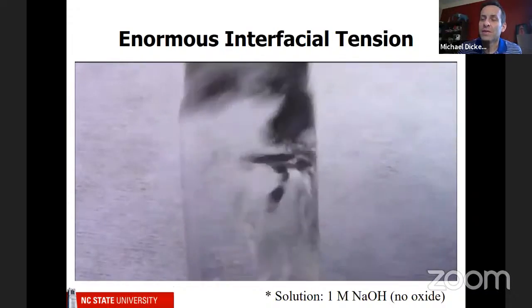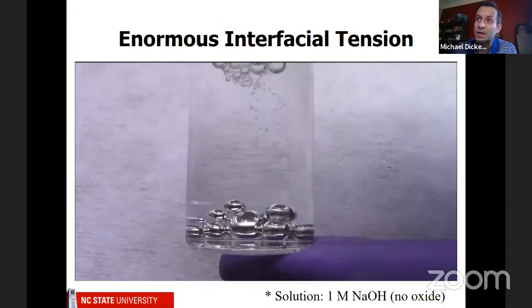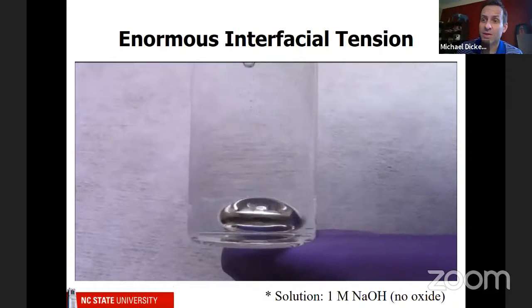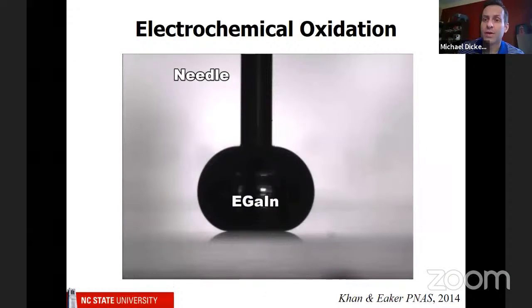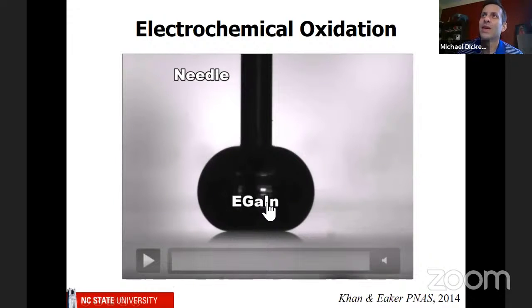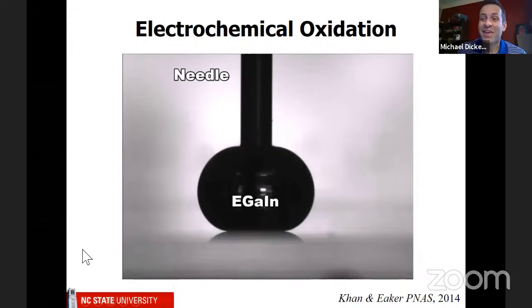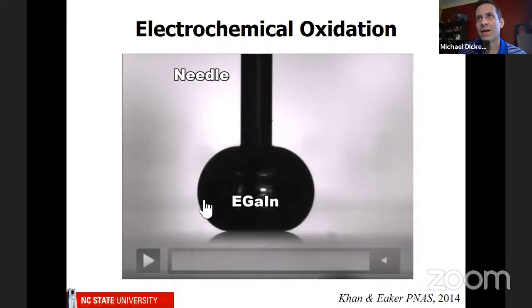So again, all the experiments I'm going to show you are in sodium hydroxide, which is this electrolyte, it's a base, and it removes the oxide layer. Okay, so here is a droplet of the metal. Again, this eutectic gallium indium, and it's sitting in sodium hydroxide. So there's no oxide layer, and because of that, you can see the droplet is very spherical. It's connected to a syringe, which is how we apply voltage, and we're going to apply 1 volt. And when we do that, all that should happen is you should deposit oxide on the surface, and nothing interesting. This should be the most boring video in the world, but let me show you.